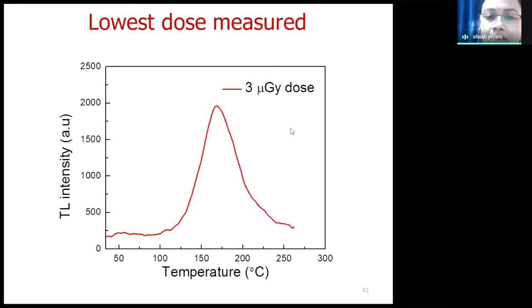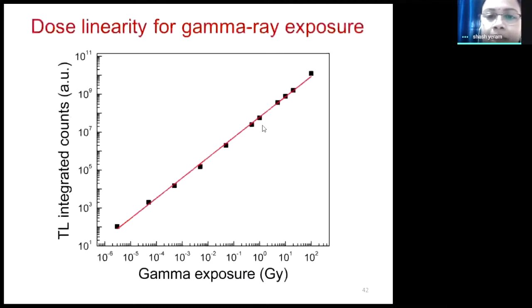This is the glow curve, we call it the TL glow curve. Here we are measuring the intensity, and this is the temperature. The area under the curve gives the amount of dose which this crystal chip has seen. Like I'm writing, 3 microgray was the minimum dose we were able to measure using this crystal, lithium tetraborate. And this is its linearity. You can see from microgray to 1 gray, even more than that, it has linear behavior.